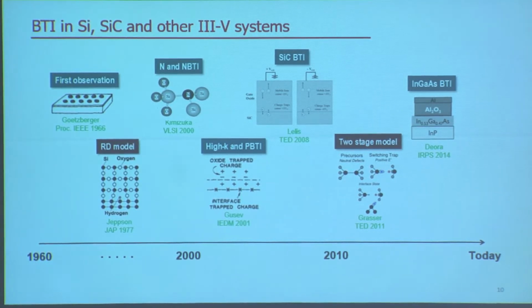Even though the observation of BTI was made very early on, and there's an established model for that, BTI was really not a big issue until the 2000s, when nitrogen was introduced to the standard CMOS process. This is because nitrided oxide has more water species and gave rise to NBTI and made it more severe compared with the previous generation of transistors. Also around the same time, the high-K dielectric was introduced to continue the transistor scaling trend. And because the high-K oxides are known for having a lot of oxide traps, it gave rise to PBTI.